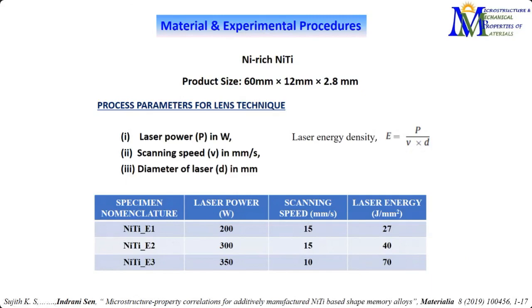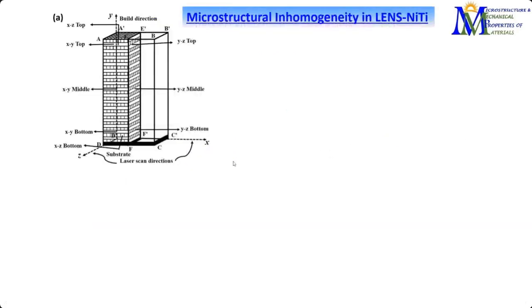Interestingly, what we get looks the same across the three components produced from the three processing energy densities. We performed a thorough microstructural characterization at the first step from various locations - top, middle, bottom, cross section, parallel to the build direction, perpendicular to the build direction, and interior of the build direction at every location.